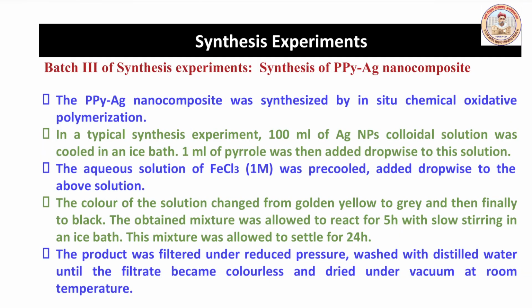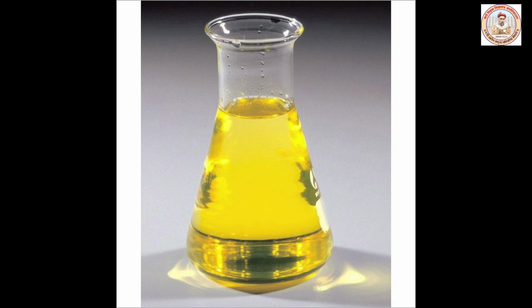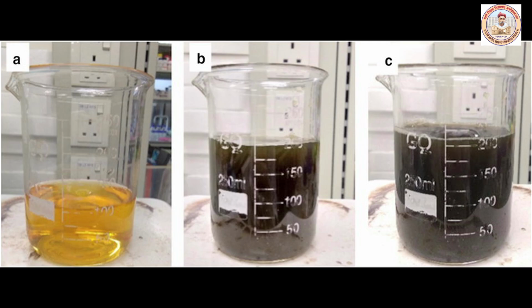The procedure in short goes like this. The PPY silver nanocomposites were synthesized by in situ chemical oxidative polymerization. In a typical synthesis experiment, 100 ml of silver nanoparticle colloidal solution was cooled in an ice bath. 1 ml of pyrrole was then added dropwise to this solution. The aqueous solution of FeCl3 was pre-cooled and added dropwise to the above solution. The color of the solution changes from golden yellow to grey and then finally to black. The obtained mixture was allowed to react for 5 hours with slow stirring in an ice bath.